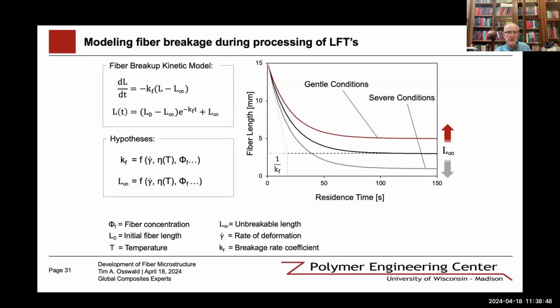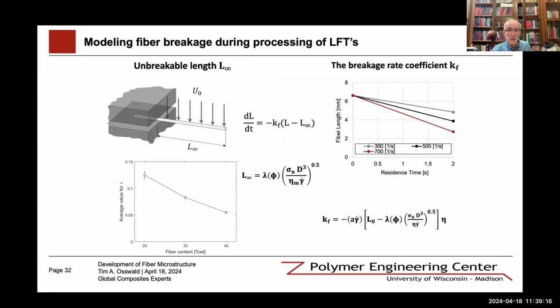And so basically, you would have a function that predicts the length if you have a constant shear stress, where you would have a length distribution as below. The question is, what is Kf, which is the breaking rate, and what is L infinity? And so we did some conceptual thoughts here. The infinite length is basically, if we just look at a Stokes flow past the fiber at a certain velocity, at which point do we reach the maximum stress at the edge in this beam, so where the beam is bent enough to be able to break,